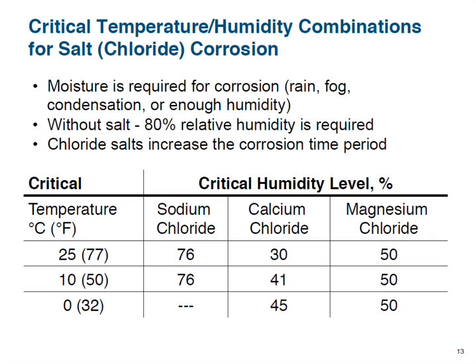Since Steve talked a little bit about the studies, and I don't want to infringe on what is going to be talked about later, I wanted to talk very briefly about what humidity means in terms of corrosion. If you do not have salt in the environment, which you would not have between the layers, then you need about 80% relative humidity to have corrosion occur. And we have a time of wetness issue, a TOW, which you might see if you're working with a metallurgist. And if you don't have a very long period of time where there is moisture present, then you can't have corrosion. If salt is in the environment, and in this case I'm looking at 3 salts that are both found in sea salt but are also used for de-icing.